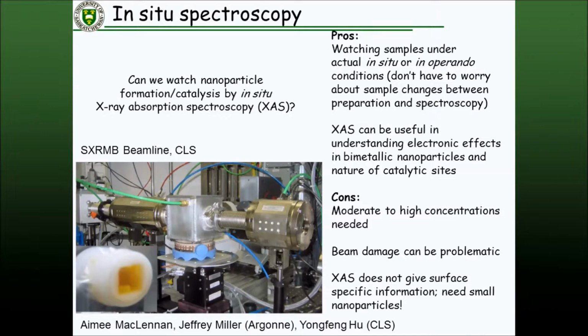There's a 5-micron polycarbonate membrane on the surface of that. There's a little stir barrel in there that is being addressed. This solution cell is sitting right in the middle of this aluminum box at a 45-degree angle from the X-rays coming in. There's a fluorescence detector over here and a transmission ion chamber over here. At high energies, we can do transmission experiments. At low energies, we can do fluorescence experiments. Now we can do things under the real conditions, to try to understand the electronic properties of these catalysts.